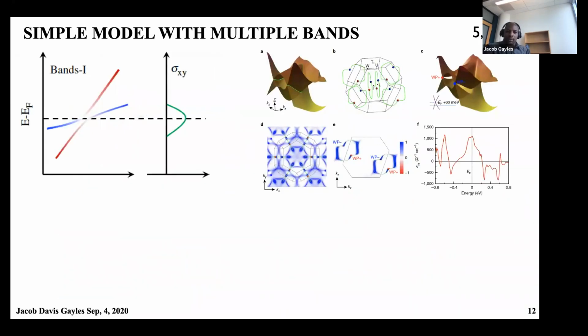So the simple model has actually worked quite well. You have things like these Weyl semimetals, cobalt tin sulfur, which has these two Weyl points, and this shows quite a high maximum of the anomalous Hall effect of about 1200 Siemens per centimeter. And this is nice because that's a very simple band structure. And what's nice about this Weyl semimetal is before spin-orbit coupling, you have this nodal line, and once you add spin-orbit coupling, this nodal line is gapped across space, except for at these Weyl points, which makes this what people can say is a true semimetal. And the fact that you have this continuous gapping across your Fermi energy, except at these Weyl points.